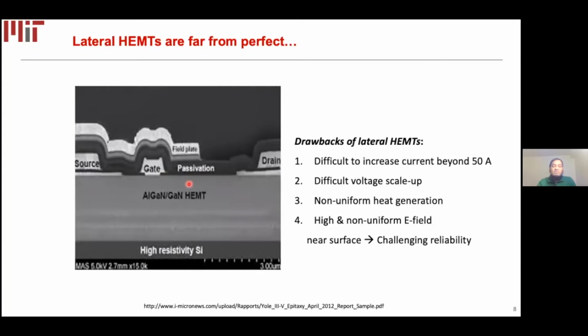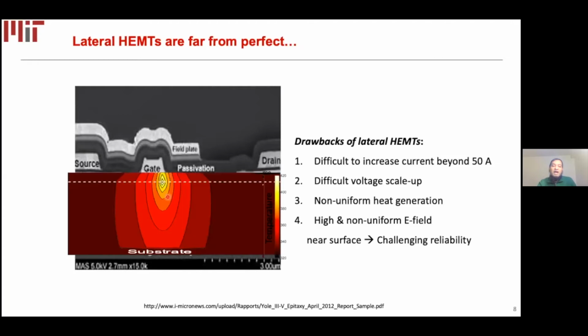The third, very important bottleneck is the heat generation capability. Since in the lateral geometry the transport is happening near the interface, when we are flowing a really high current, all the heat is concentrated near the surface. And the bulk of the substrate is unused, and it's not helping to dissipate any of the heat. And the final problem of the lateral geometry is the non-uniform electric field. In a lateral geometry, the electric field is concentrated at the edge of the gate, and that makes the reliability of these devices very challenging.